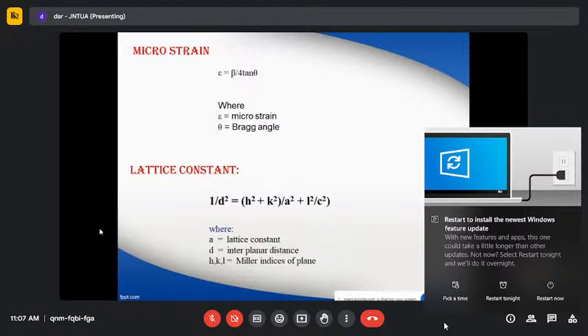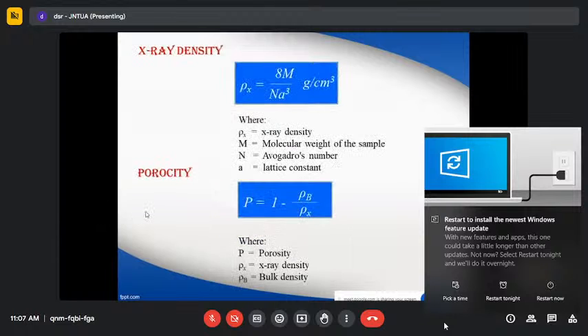Further, apart from the lattice constant, the porosity was also evaluated. The porosity has been calculated using the formula. The porosity achieved values increasing from 13.1 to 27.3%. The porosity will have an influence on various magnetic, electrical, and ferroelectric properties.